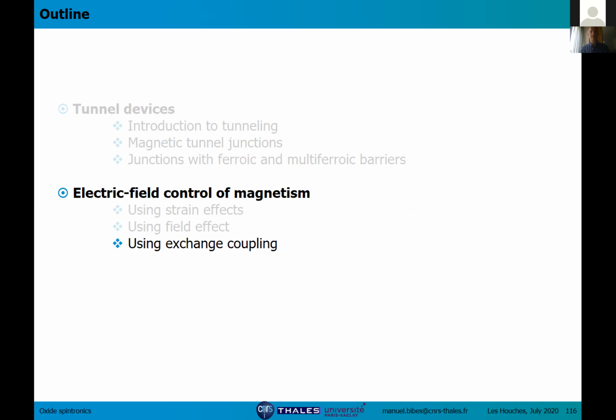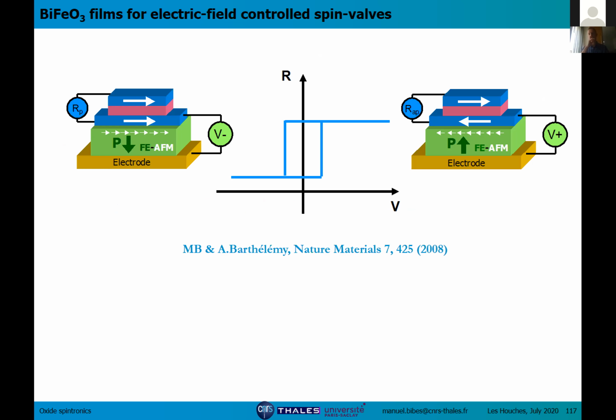And the last part is using exchange coupling. So I will come back to the multiferroics. So this is an example of a device that one could make by controlling magnetism with an electric field using exchange coupling. This is what we call magnetoelectric random access memory. So you have here a spin valve, which can be a tunnel junction. So you have your two ferromagnets separated by an insulating layer or maybe by a metallic spacer like copper. And this sits on top of a multiferroic, which is ferroelectric and antiferromagnetic.